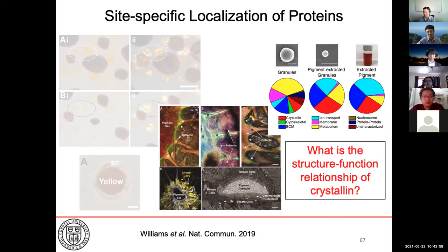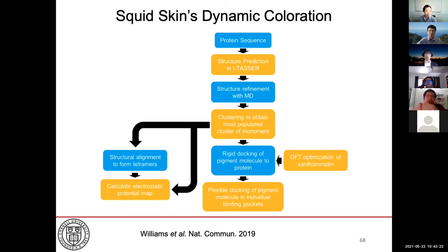So this leads us to ask, what is the structure-function relationship of crystallin? To answer this question, we will need to dig deeper into the molecular details, which are usually beyond the means of experimental methods. And therefore, we use multiscale computational modeling to complement this whole suite of studies that were done by my experimental collaborators. And as this is the very first comprehensive proteomics of the squid chromatophore, the protein structures of crystallin and reflectin are still unknown. And therefore, I turn to homology modeling to provide an initial prediction of the structures. And then I refine the predicted structures using replica exchange molecular dynamics, as I described earlier. Now, with these different predicted structures in hand, I can analyze a very wide variety of the structure-function relationships of these particular proteins.